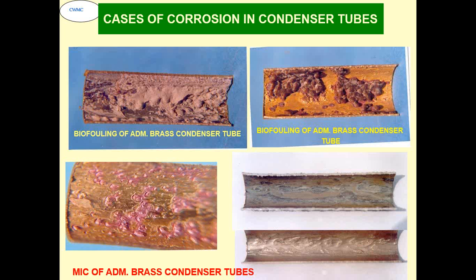A typical biofouling in a river water system is what you see in this picture. On top of this there was a calcium carbonate scale which was mechanically removed. This is the condition we saw, and this is after chemical cleaning of the same tube. You can see a chain-like structure, which has been formed because of microbiologically induced corrosion below the deposit.